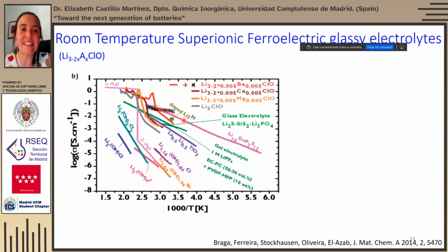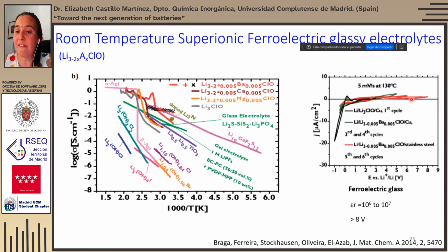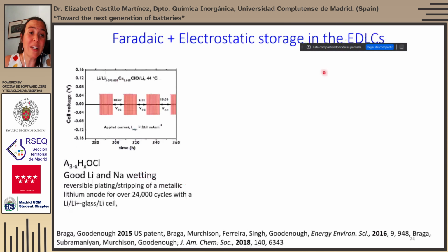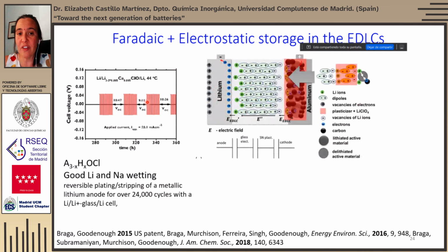In some sense, these materials are not as sensitive as sulfides, although they have to be treated with some care as well. This type of glass electrolyte additionally has a very large voltage stability window in excess of 8 volts. You can see they don't decompose at 8 volts above lithium. And what is very important, they have very good wetting properties towards lithium, and they enable the reversible plating and stripping of lithium metal. They can be plated and stripped for more than 24,000 cycles in a lithium-glass cell. And very interesting features are being shown by this glass electrolyte, which seems to also contribute to the capacity of the materials.